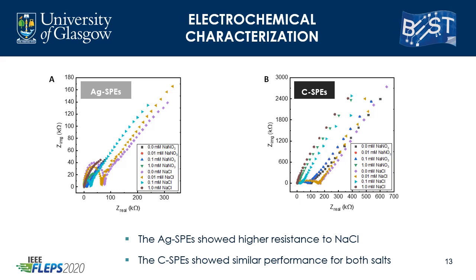For carbon electrodes, the charge transfer resistance decreased with increasing concentration of solution as well. However, a higher overall resistance was observed. It could be due to more ions being involved in the electrochemical double layer formation, effectively increasing the capacitance of the electrode. Similar performance was observed for both salts, both the nitrate and chloride solutions. This showed the stable performance of carbon electrodes when salt is present in the solution.